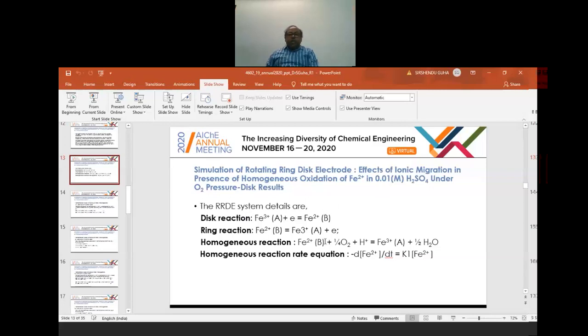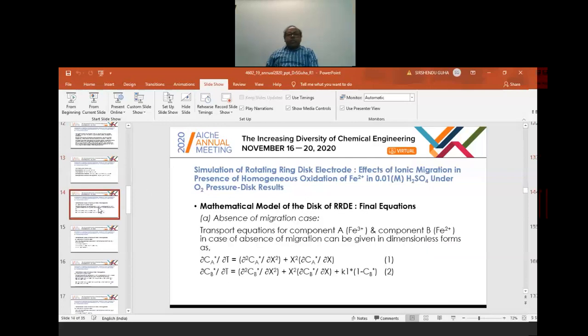B to A also. The homogeneous reaction is given as a first order rate equation, that is, minus d[ferrous]/dt equals k1 times [ferrous]. Now this is the mathematical model. The absence of migration case can be given by these equations as the transport equations. These are available in my literature, so one may refer to it.